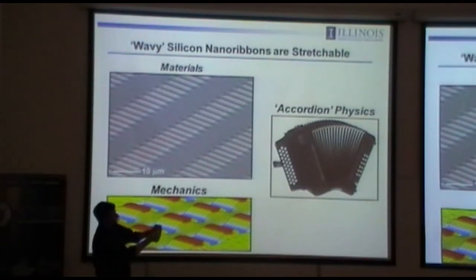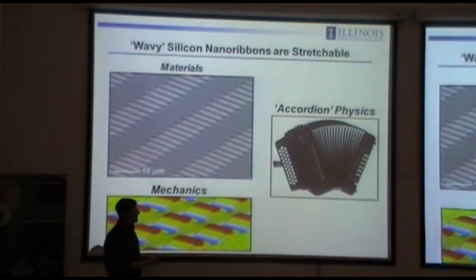And it's in a geometry that allows an effective end-to-end stretchability in a way that doesn't exceed fracture thresholds in the silicon. So you take this thing, you can stretch it out. The way the silicon wave structure responds to that stretching deformation is through changes in the structure of the waves. So the wavelengths go up and the amplitudes go down. And likewise, when you compress it, amplitudes go up, wavelengths go down. And so back and forth like that, completely linear, elastic response dominated by the substrate, and now you have a very high performance active semiconductor on top. So it's essentially accordion bellows physics. There's not that much beyond it in terms of just conceptually thinking about it.